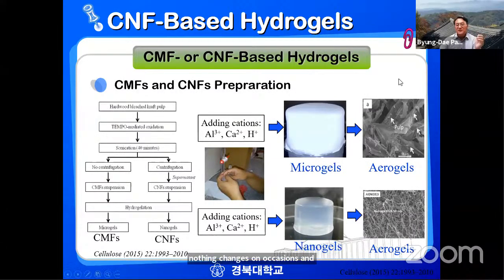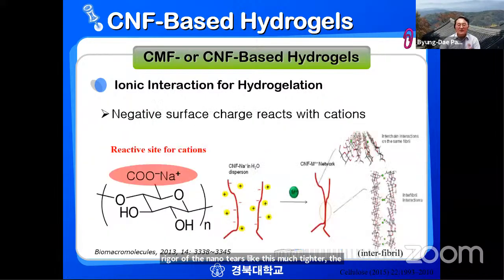And then this idea is very simple to make hydrogels. As you know, when you have TEMPO oxidation, CNF has surface negative charges, sodium carboxylate groups. And then you just add the cations, aluminum trivalent cations or divalent, or just hydrochloric acid to provide the protons. And then we add these different types of cations to the TEMPO-oxidized CNF suspension and the microfibers, and then we get the microgel, and then we also freeze-dried the aerogels. And then we add the same different types of cations to the cellulose nanofibers, and we get the nanogels like this, with much tighter inter-fibrillar morphologies.